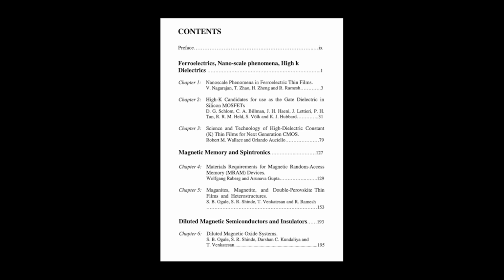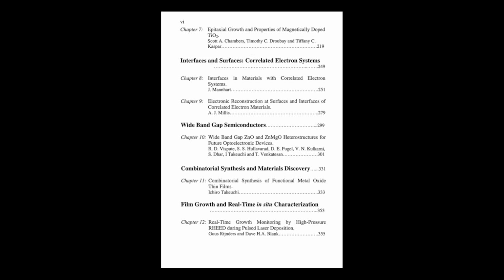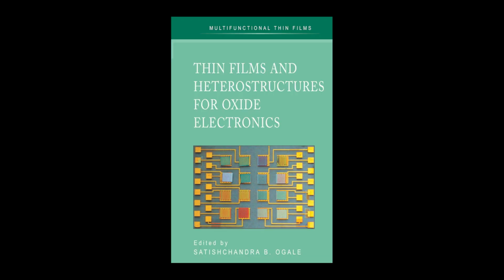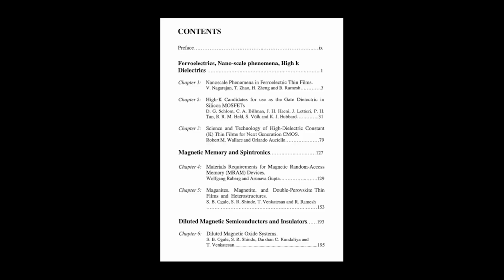Even if you solve the stability problem, new issues pop up. Always the way, isn't it? Yeah, Chapter 3 dives into the practical integration headaches. The first is just a general trend they noticed. There's usually an inverse relationship between K and the band gap. Push K higher, the band gap tends to shrink. Generally, yeah. Which means you might start getting more leakage again, defeating the purpose. It's a trade-off you have to manage.